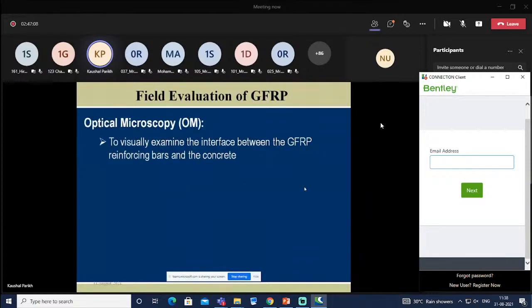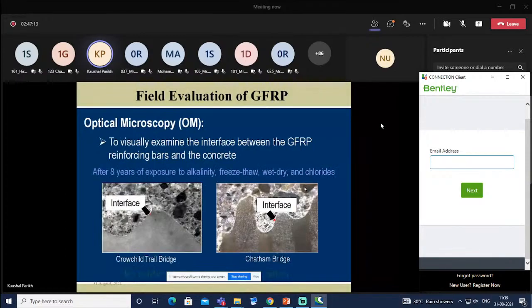But even so, a slight input has been given here. First, optical microscopy is used to visualize or examine the interface between the GFRP reinforcing bar and the concrete. Here it is to be noted that after 8 years of exposure to alkalinity, wet-dry cycles, and chloride ingress, no evidence of damage or deterioration is shown, or very little damage, which can be visualized from the optical microscopy.